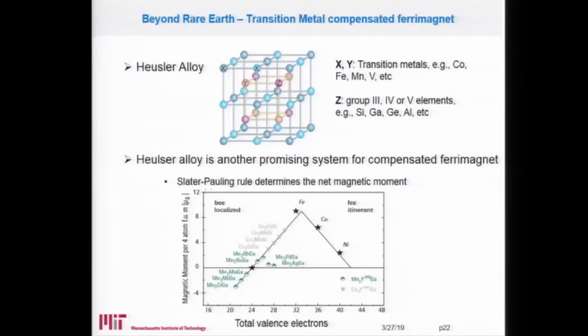Well, we turn our attention to another system which can also have zero moment, but is composed of other elements and not rare earths. This type of material is known as Heusler alloy. Heusler alloy is in general composed of 3 different elements, X, Y, and Z. X and Y are transition metals, for example cobalt, iron, vanadium, manganese. And Z are group 3, group 4, or group 5 elements like gallium, silicon, aluminum, etc. When you make this kind of Heusler alloy, it turns out that it can also form ferrimagnets whose magnetic moment can be tuned almost equal to 0.